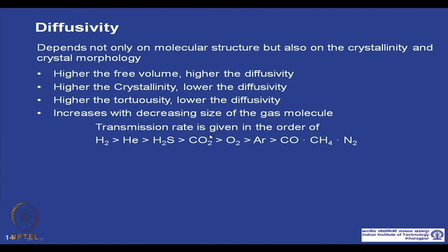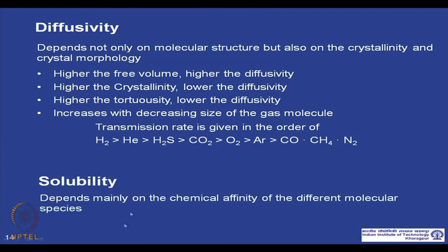So, given everything else is the same, the transmittance rate will go up for a smaller gas compared to a larger gas. The second parameter responsible for permeability is solubility, and the solubility of a gas in a polymer depends upon the chemical affinity between the gas and the polymer we are talking about.